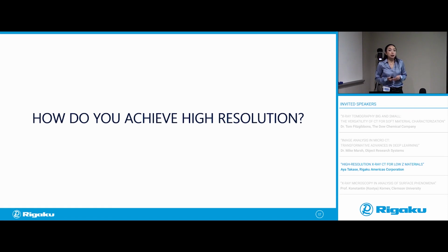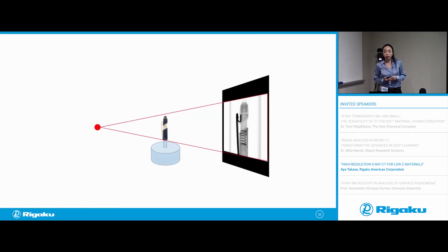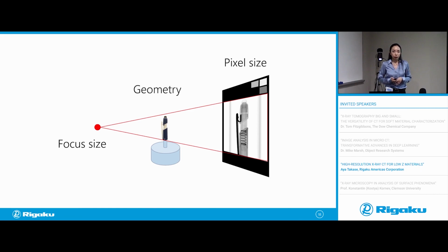So typical X-ray CT scanners look like this. You have an X-ray source here, and you have a sample, and you will be rotating this sample for the scan, and you have a 2D detector at the end. The resolution of the image you're going to get from this system depends on the focus size and the detector pixel size. And for those two, in general, the smaller, the better. But it also depends on the geometry we use. This is a simple cone beam geometry, but there is another geometry you can use for high resolution measurements.